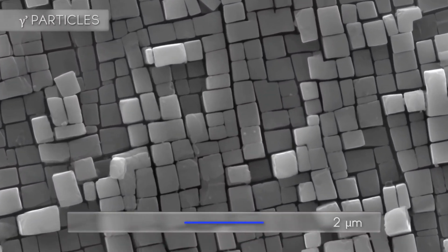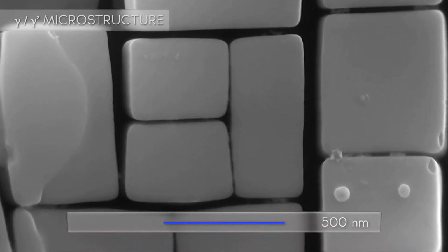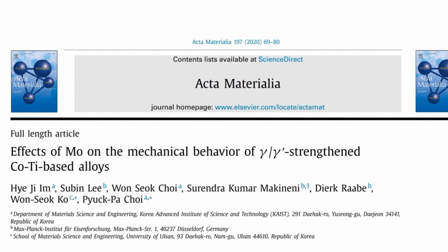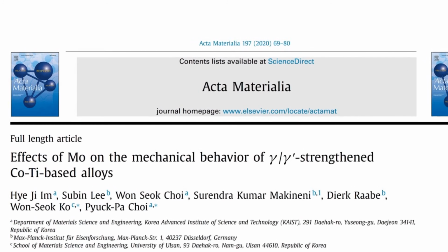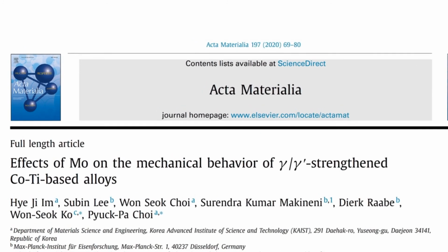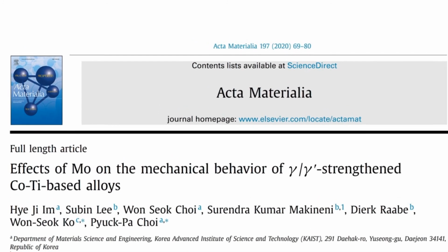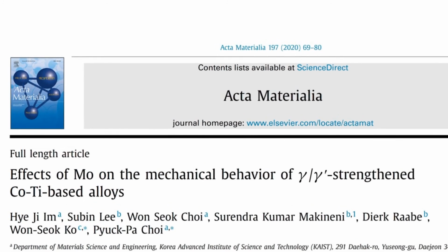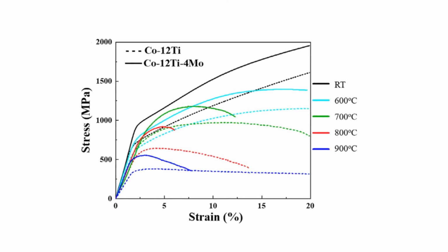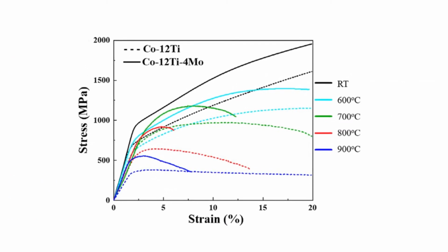Thus, there is an active search for alternative systems with enhanced thermal stability. Among them, cobalt-based alloys, strengthened by coherent gamma-prime precipitates in a gamma matrix, a disordered face-centered cubic solid solution, have attracted interest, due to their excellent hot corrosion resistance in harsh environments, and the potential for a higher melting temperature compared to nickel alloys.